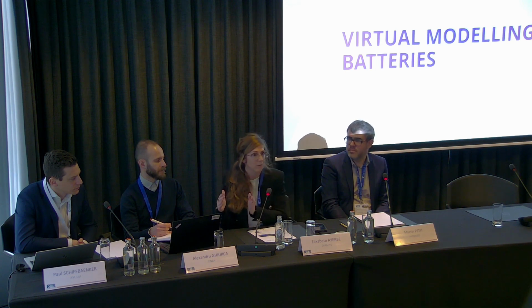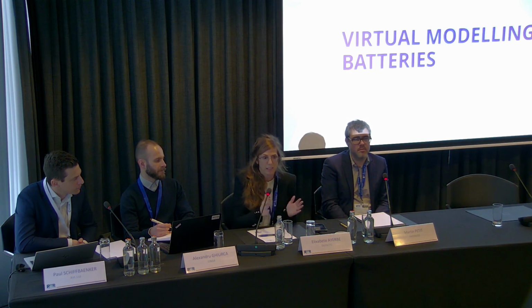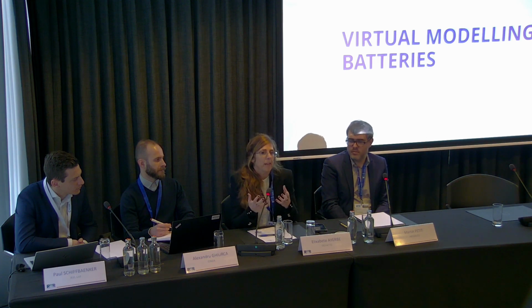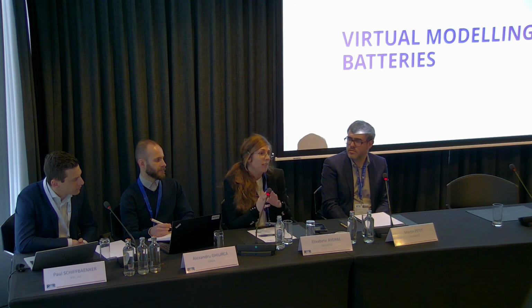Yeah, so within the DEFACTO in particular, we were very much focused on the lithium ion and very much on the steps of roll-to-roll application. So, yeah, electrode microstructure level, obviously electrolyte filling, so liquid scale, liquid lithium ion. So it's not only about chemistry dedicated, because even though you don't have silicon, you will have certain expansion within the lithiation. So the mechanics is always really important, even if you need to think from cell to pack. For instance, if you need to design properly the module or pack, you need to take into consideration any swelling of the cell. So I would say that in the DEFACTO we were very much focused on the lithium ion, even though,